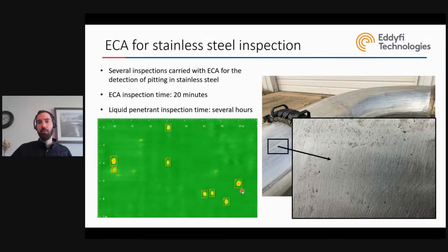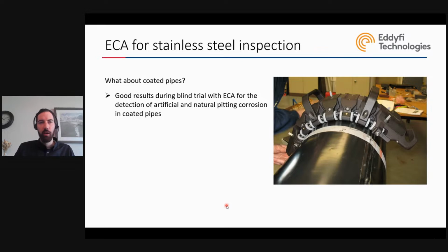Just by looking at the amplitude of your signal, you know that those amplitude and those indications are not cracks. They're not SCC. They're not very important or not very deep. But you know at least that there is some indications of pitting. And the boxes that are here on top of each pitting, they are put there automatically by the software. So you don't have to go through your long data file and report each of them. They are all automatically put on the C-scan, and then you can just report them all at once. Otherwise, it would be very long. It would be just like in visual inspection.